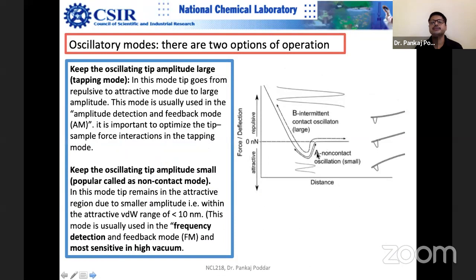As I mentioned, there are two ways you can do that. You can keep this oscillation quite large, which is the normal tapping mode, or you can keep this oscillation small, and that is called the non-contact mode. Normally in the intermittent contact mode, we do the measurements in amplitude detection mode. We look at the amplitude change of the cantilever, and that gives us information about the surface properties, including topography. In the non-contact mode, we normally go to frequency detection, and we do these measurements in ultra-high vacuum,